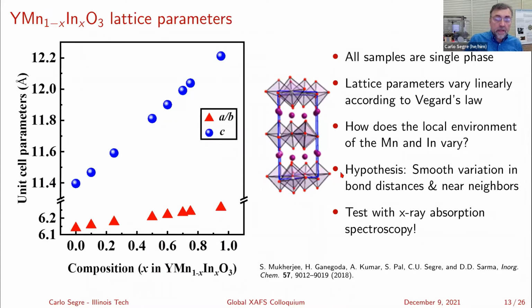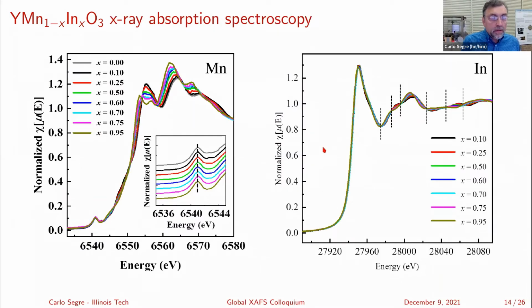So when we first started studying these, we took a lot of data on all these samples, and we then started fitting them with what we thought was the standard solid solution, random mixing of the materials, and we got some answers, and we got fits. But the fact that we presupposed that we had a solid solution that was well mixed gave us a problem when we looked at the XANES. So we started staring at the XANES, and we realized that in fact things were not as they seemed to be from a pure solid solution random mixing perspective. That's what had been done for the DFT calculations. That was what we had done our fits for, and we got reasonable fits. It's just that they didn't make a lot of sense. The parameters weren't coming out very well in the EXAFS. So we realized that in fact we should look at it in a different way.